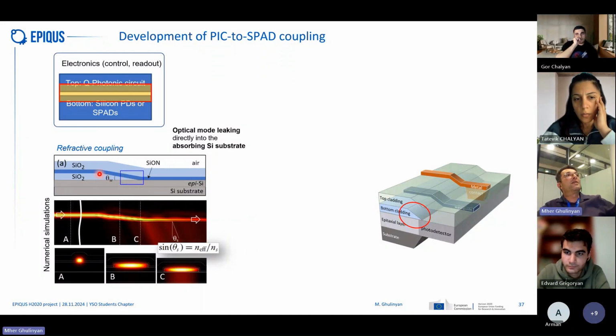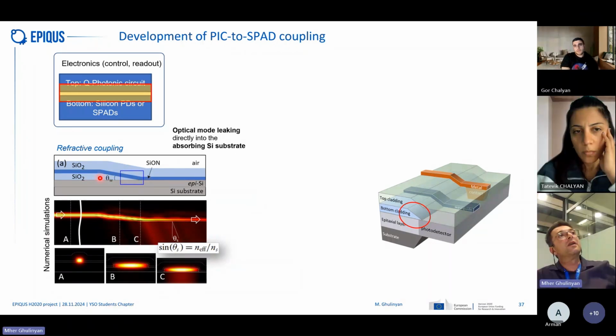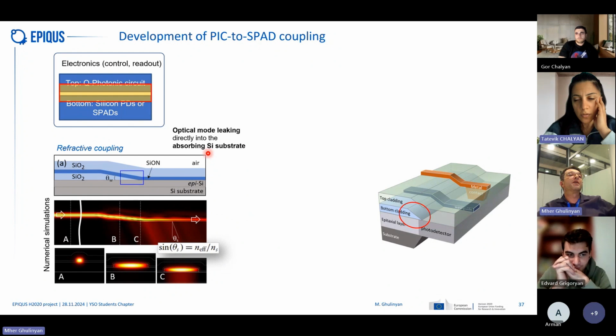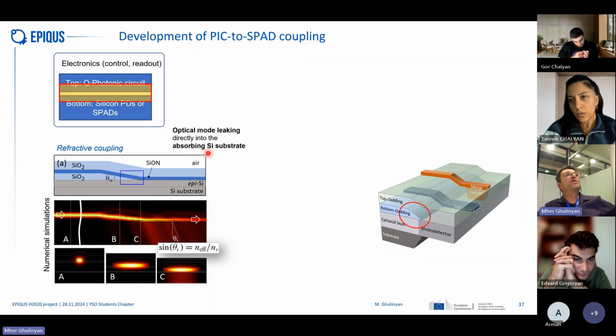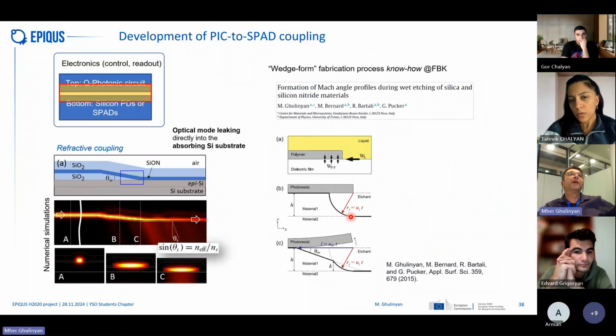The problem is that realizing a triangular shape in normal microtechnology with wet etching is impossible, because wet etching is isotropic etching. Probably you know from your studies at the university, or if you don't know, just to say that if you etch an amorphous material by putting it into an acid, for example, it will etch the same way. You will dissolve your material in all directions in the same way, and that will create a circular profile. Okay, so the etching. Here is a protective mask, and this is where you have your acid, for example, and you want to etch your dielectric film. When the dielectric film starts to etch, it etches in all directions, and at the edge it will start to create a circular pattern.